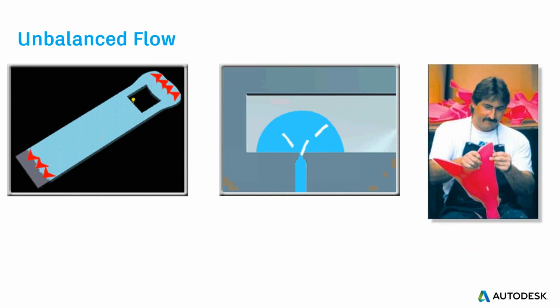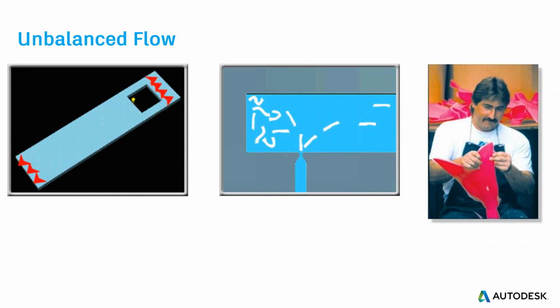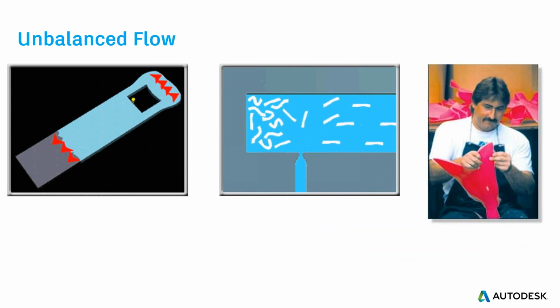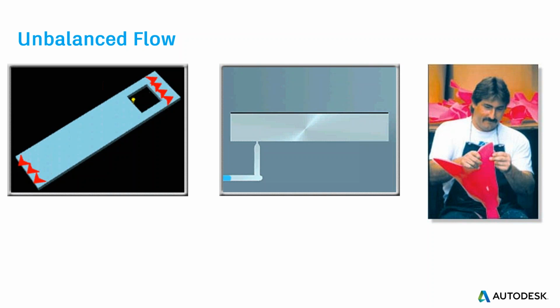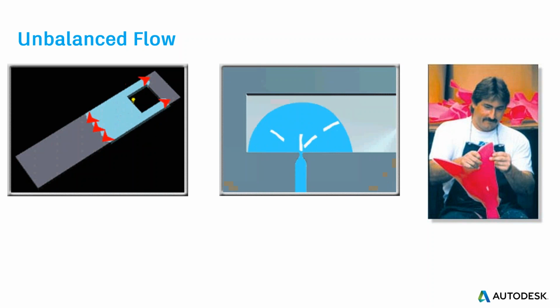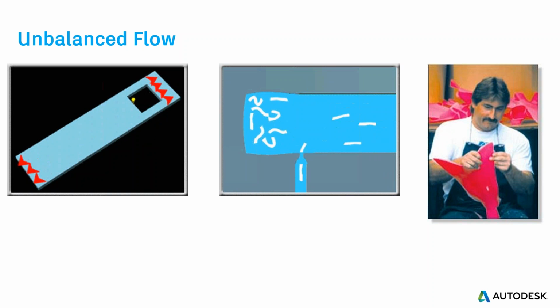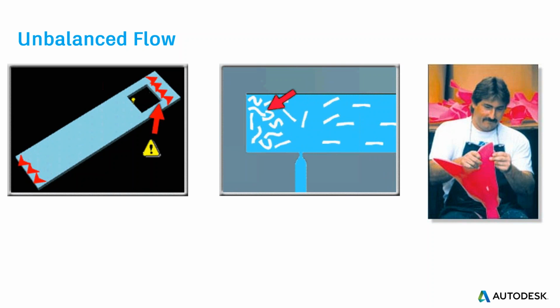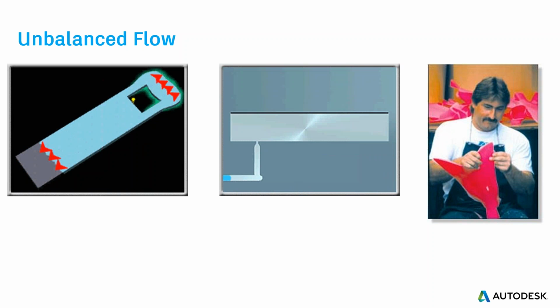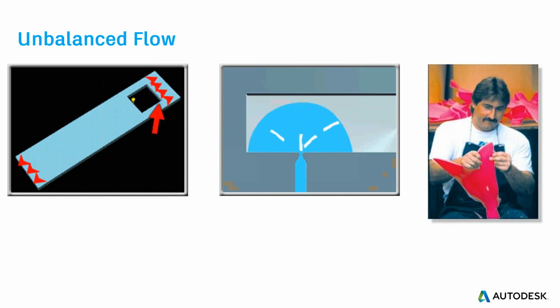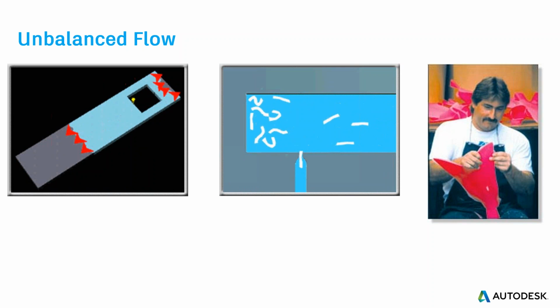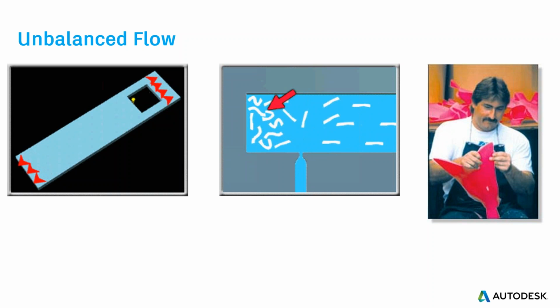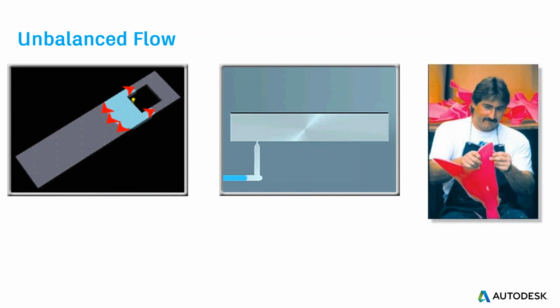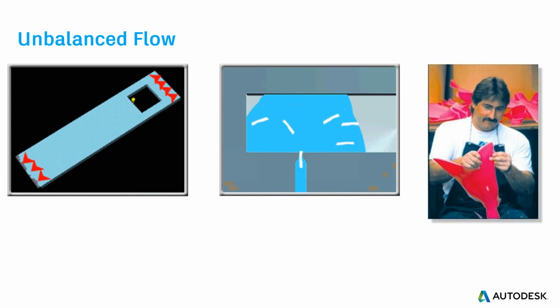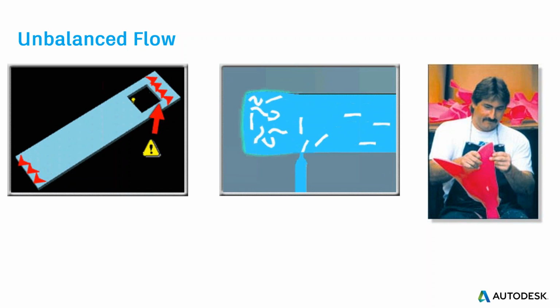So if we start with some of the basics, one of the main issues of poor product quality can be that of unbalanced flow in the cavity. So this means that some areas are filling before others, and while they're still filling other areas, these areas can become overpacked. They will shrink less. Lower shrinkage will mean different dimensions, and also it can induce warpage in the component. It can also increase clamp force, and the mold may actually open and flash. And we still see people sitting by machines trimming off flash. And this isn't always due to mold wear. It can be because of this unbalance where the mold is open locally to let material out.